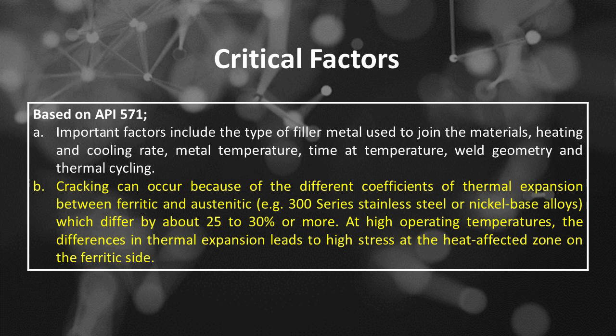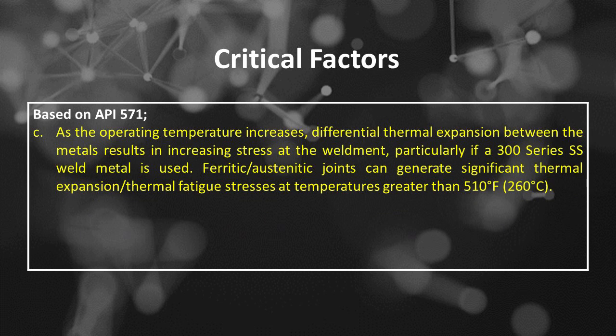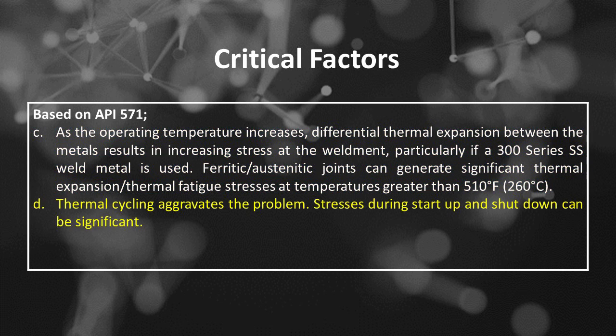At high operating temperatures, the differences in thermal expansion leads to high stress at the heat-affected zone on the ferritic side. The third is as the operating temperature increases, differential thermal expansion between the metals results in increasing stress at the weldment, particularly if a 300 series SS weld metal is used. Ferritic/austenitic joints can generate significant thermal expansion/thermal fatigue stresses at temperatures greater than 510 degrees Fahrenheit, or 260 degrees Celsius. The fourth is thermal cycling aggravates the problem.